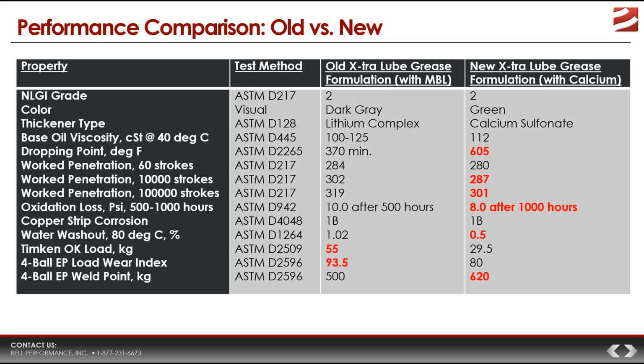Dropping point is not the maximum temperature at which a grease may be used. That maximum temperature is always lower. Grease manufacturers never recommend that you use grease all the way up to the dropping point. Typically, the upper operating limit for a grease is recommended to be 100 to 150 degrees below the dropping point.